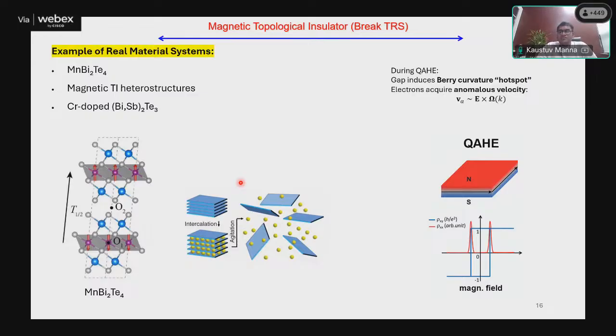But by external magnetic field, you can polarize these spins in the same direction also. You need a little bit high magnetic field. As a consequence, you can understand that this compound you can just cleave with natural cleaving, like what people do with device fabrication using a 2D material. You can control it layer by layer.